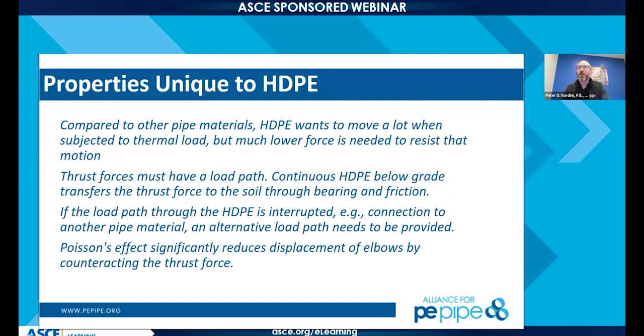And then in the middle here, when we think about longitudinal restraint of pipelines in general, we need to really be careful with these hydraulic thrust forces and make sure that we have a good load path. So when we're looking at HDPE, it's a continuous pipe material. We looked at the fusion connections. So the pipe is continuous, and when you're looking at a below grade application, the thrust forces in the pipeline are really transferred to the soil through bearing and through friction. If you're looking at above grade pipe, maybe you have to transfer those loads to some anchor supports.